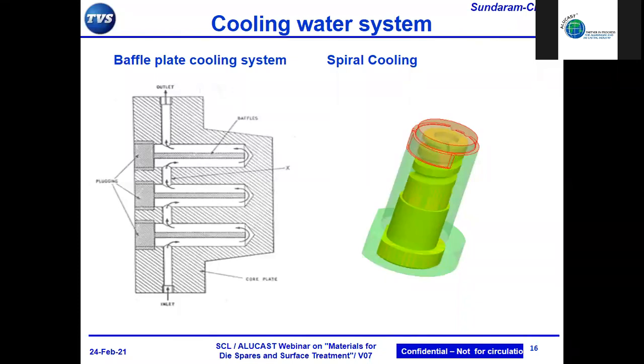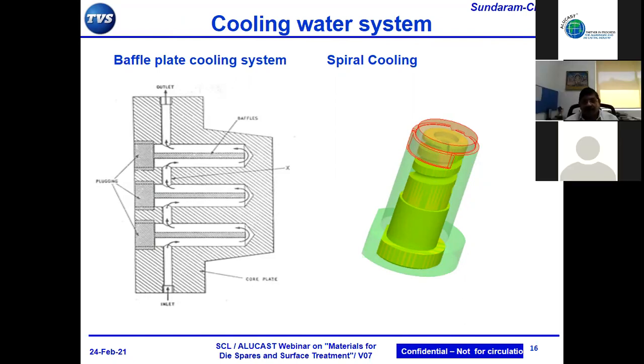So what do we do in such cases? These are some of the things which we need to really work around so that we have a much faster solidification, so we do not give enough time for the phenomenon of soldering. What happens when soldering happens? You have a chemical interaction between the die surface and the liquid metal, and that is where soldering occurs. So once you have a rapid solidification situation where you have fast heat extraction from the liquid metal, soldering can be avoided. So these are some of the things which we need to build into design and material selection, which enables such complex requirements for the component.